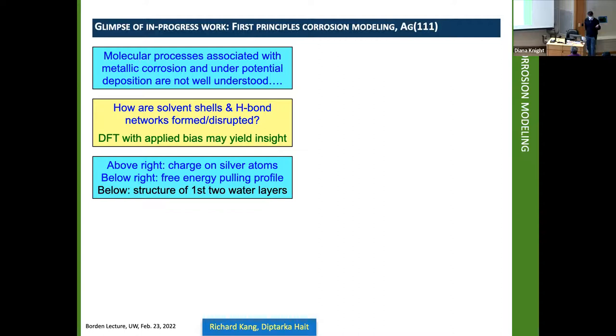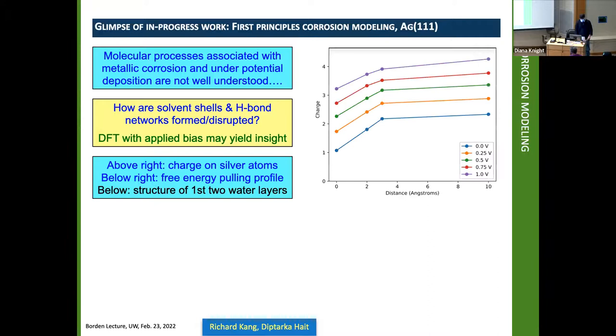How are they degraded? Here's a little bit of data to show you that this can be done. We're plotting here as a function of distance. This is pulling a silver atom out of a silver 111 surface. This is the net charge on the silver atoms, and what you see is that charge shifts by one electron as you go from zero angstroms of pulling to 10 angstroms of pulling.